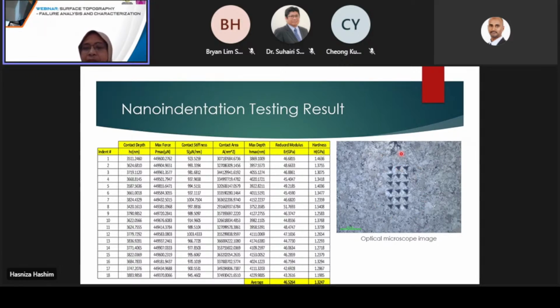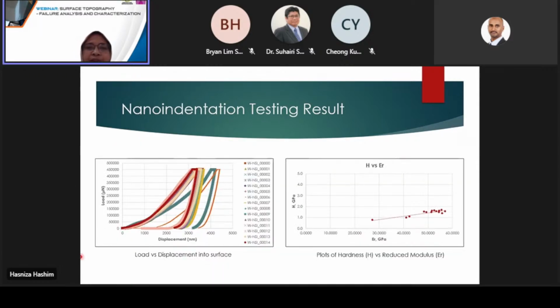Take note that this image can be visible via the optical microscope only if the force that we applied is quite high. Otherwise, we can't see it through the optical microscope. From the result, we can also plot the P-h curve, and also the hardness versus reduced modulus graph to see the distribution, or also see if there are some outliers in the data out of the 18 indents that we have performed.